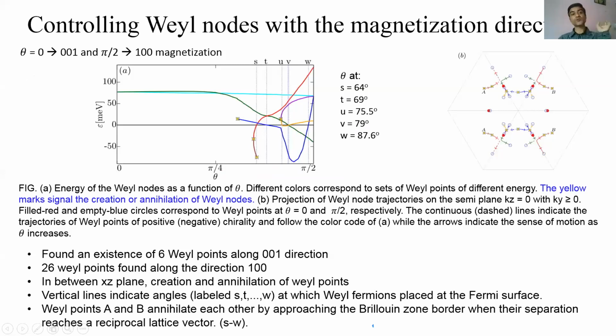As we rotate the magnetization, the very interesting thing you find in this picture is that the Weyl points lie somewhere around 70 milli-electron volt above the Fermi level, and up to a 45-degree rotation, they remain on the same energy scale. But as you go further, what you find is they are moving closer and closer to the Fermi level.